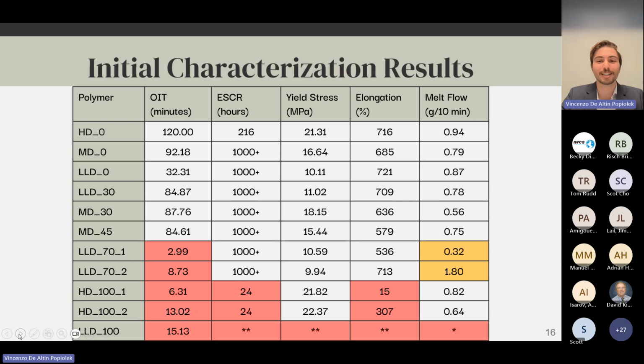Finally, for the high PCR content blends, as expected, this is where we saw our failures and our issues that we'll have to try to compensate for in blending. First of note, the linear low density 100 sample, we see that there's a lot of asterisks. For the asterisks for melt flow index, while there is no industry standard for melt flow index, it was still deemed a failure, as rather than flowing through the die during testing, the polymer actually flowed around the die. So this was deemed to be unusable on the Prysmian group's lines, and thus was not subjected to further testing, noted by the double asterisks in the other categories.